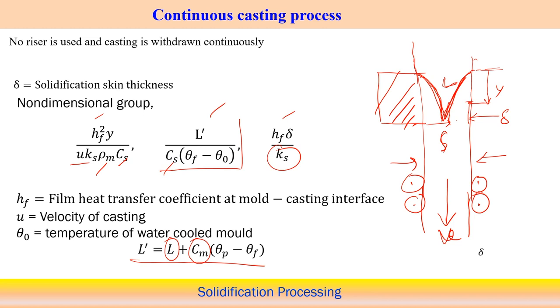So we can estimate the extent to which y can go to achieve complete solidification in a continuous casting process, because y is variable, depending upon the process parameters; this value can be extended up to a certain extent. That is why we use the non-dimensional parameters, and based on them we can calculate the other parameters also. This is the usual practice to analyze the continuous casting process. There is not much need for the solidification time here, because we have already calculated the solidification time in the case of the copper mold, whether it is water cooled or not.